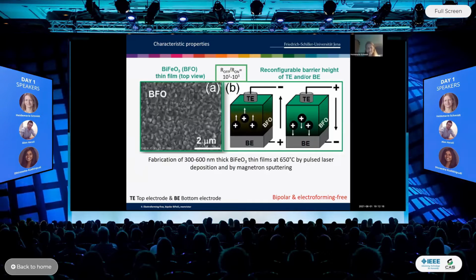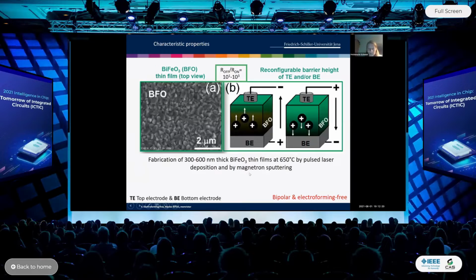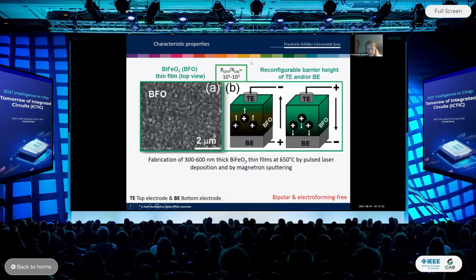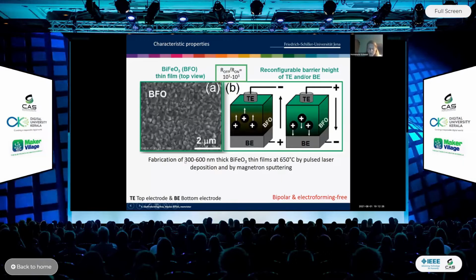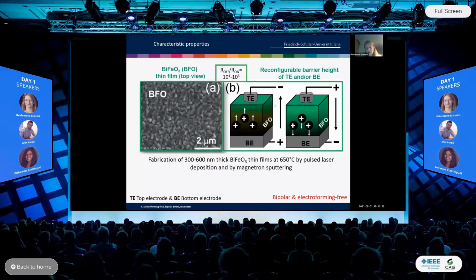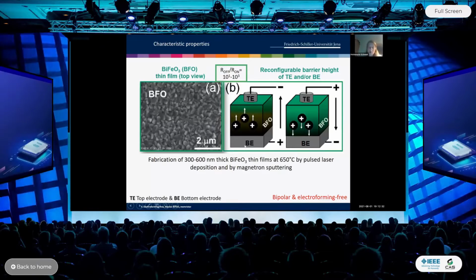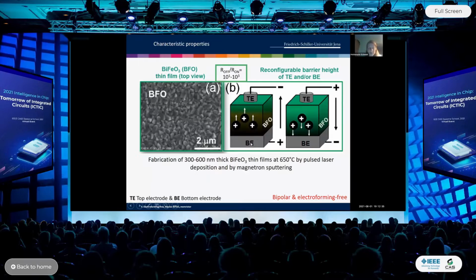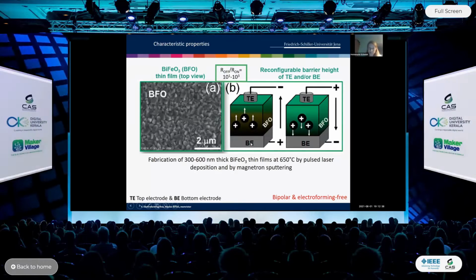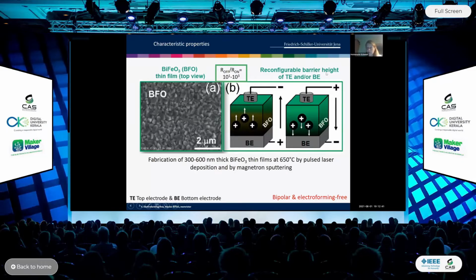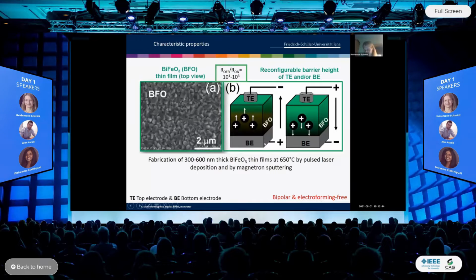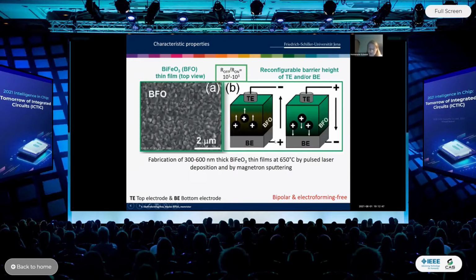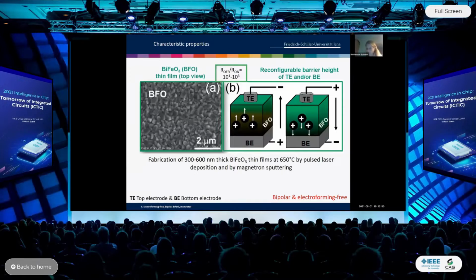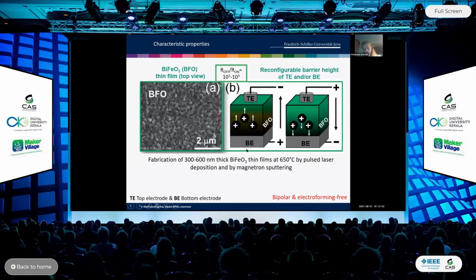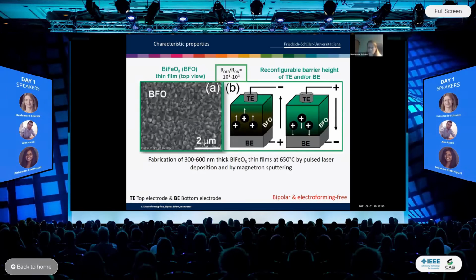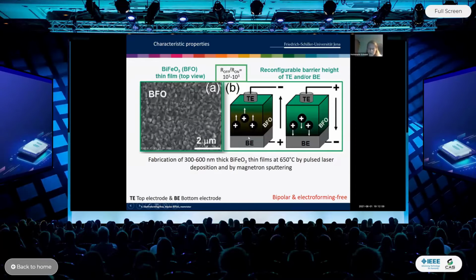Just to give you a small idea about the structure of those materials: the bismuth iron oxide memristors we are developing have a typical thickness between 300 and 600 nanometers, and they are deposited on a bottom electrode, which is typically platinum, by pulsed laser deposition. Where does this reconfigurable barrier height come from? Just out of luck, one of my first students working on this research topic used some titanium in the bottom electrode material during the growth. This was out of luck. And this titanium plays a very important role.